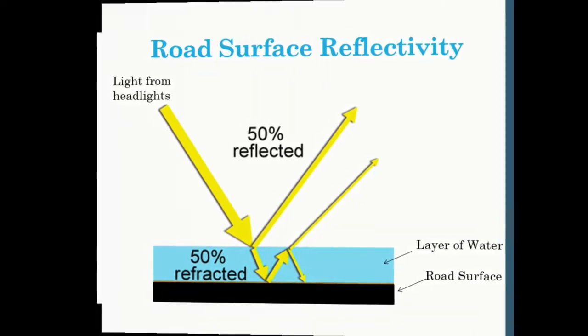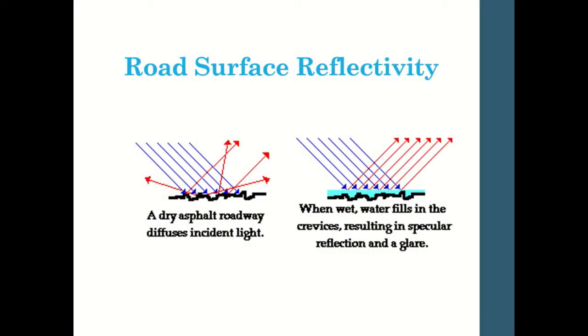In addition to that, ideally, you want the surface to be rough so that the light isn't all coming back to you in a concentrated beam. When the surface is rough, it's being reflected at different angles, so you're able to see generally and not everything is being shone right back into your eyes, all right? But when you have the layer of water on the surface, it's smooth. So it creates a barrier between the surface of the road and the light itself, so that everything is coming back to you. If you drive at night when it's raining and the light hits the surface, you're seeing a concentrated beam of light, and that affects your ability to drive and see clearly.